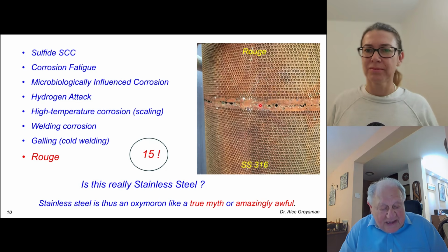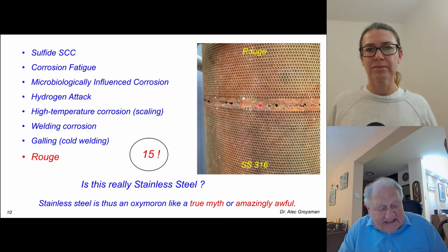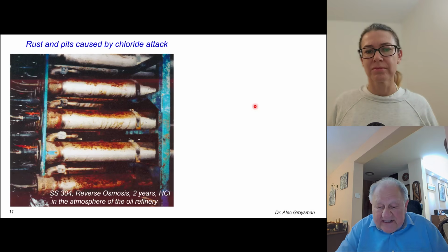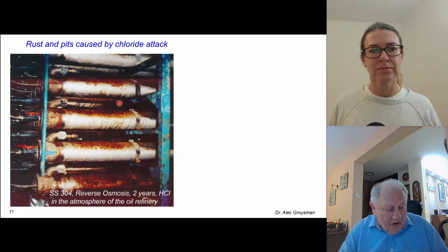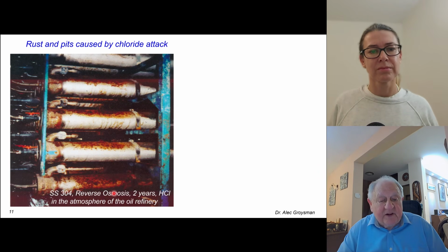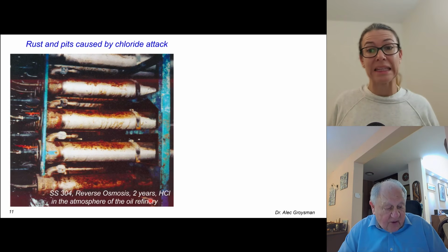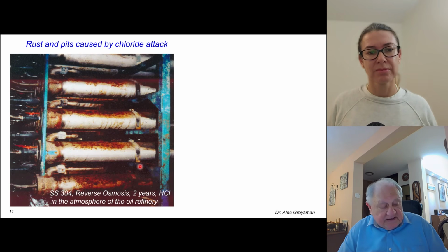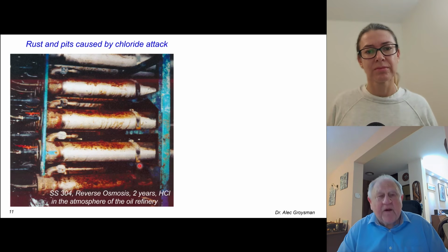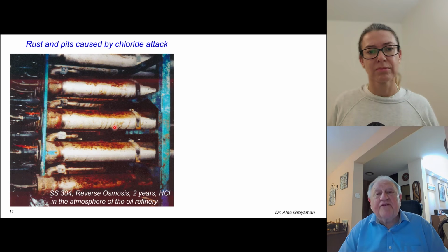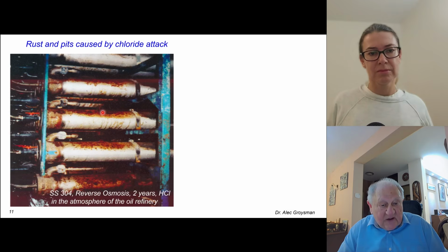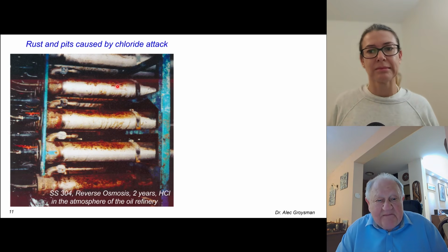If people do not know under which conditions stainless steel is truly stainless, this can lead to catastrophic circumstances. Here is an example: formation of rust and pits caused by chloride attack on stainless steel 304 tubes at a reverse osmosis unit. After 2 years of service, a tank for the storage of hydrochloric acid was erected near this unit. Once a week, a truck with concentrated hydrochloric acid was unloaded. Certainly, HCl vapor flew away and reached the stainless steel tubes. It condensed with water vapor on the surface of the tubes. You see the results after only 2 years. This is rust and pits with holes.